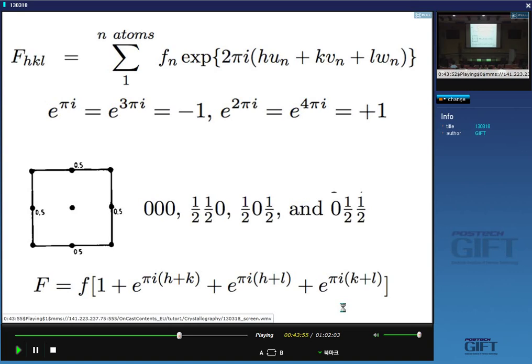Now, here is our cubic F cell, and let's say we have copper, so there's a copper atom at each lattice point. And the coordinates of the atoms are 0, 0, 0, and then at the face center, so half, half, 0, half, 0, half, and so on. So all I have to do is write the expression for the structure factor in terms of a single copper atomic scattering factor. When I substitute 0, 0, 0 into this, it's just exponential 2 pi i into 0, and exponential of 0 is 1. Okay, so I get a 1 here. When I take half, half, 0, I will have h upon 2, k upon 2, and 0, and therefore I get this term. I've now lost the 2 because it was h upon 2. Yeah, everyone happy with that? And similarly for half, 0, half, and 0, half, half.